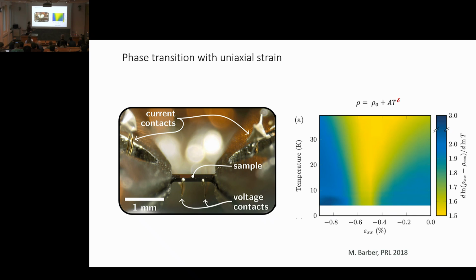There's a quite famous experiment for strontium ruthenate with transport, where they took a sample and strained it from both sides. Those two are anvils which press the sample in the middle, and they measure the resistance, temperature dependent. At zero strain, which is here on the right side, quite obviously, we have our Fermi liquid. This is the plot of the exponent of this T dependence. So on the right side, we have again our T squared law.